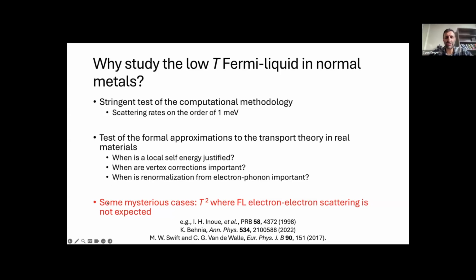And then the main motivation and kind of what will serve as the basis of this talk is that there are some, I will say, kind of mysterious cases. And those are cases where a T squared scaling of the resistivity is observed, but Fermi-Liquid electron-electron scattering is not really expected in the regime that it's observed.